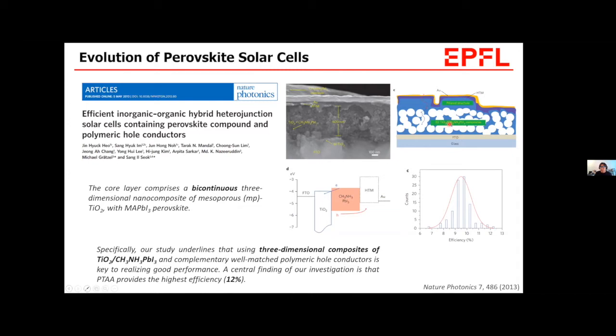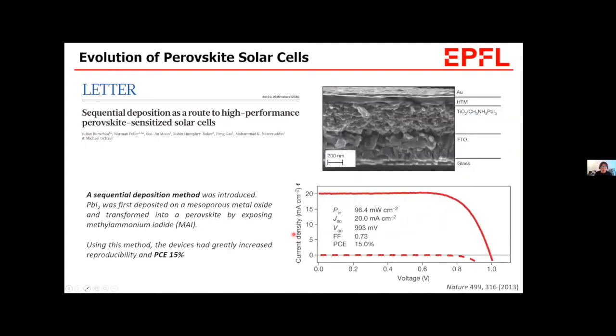This work proves that the perovskite layer itself can be thicker. And in this work, we are going as time goes by. Now we are in 2013. So they first showed this sequential deposition method. Now we simply call it the two-step process.